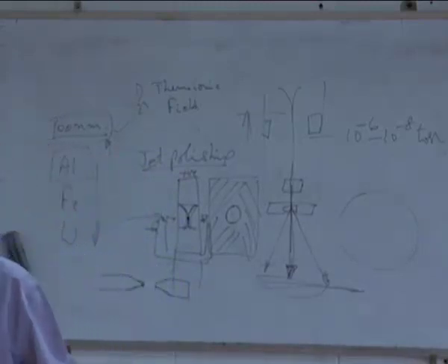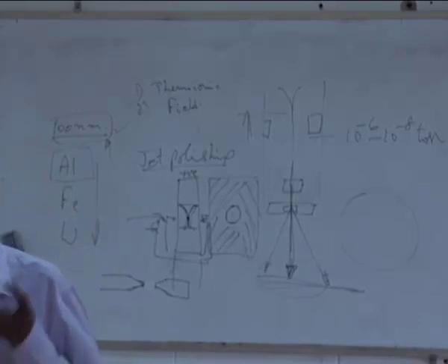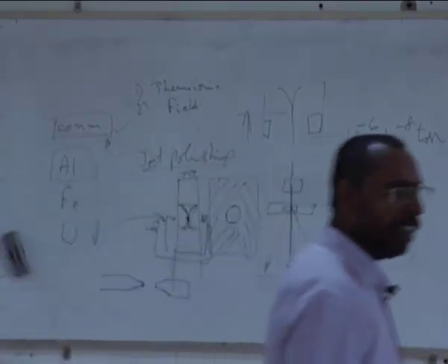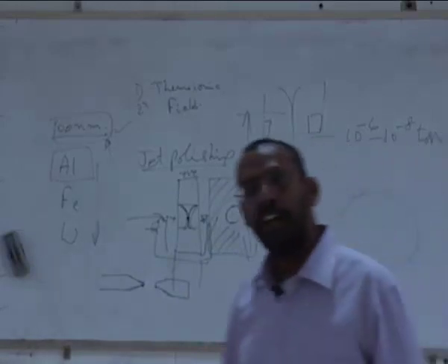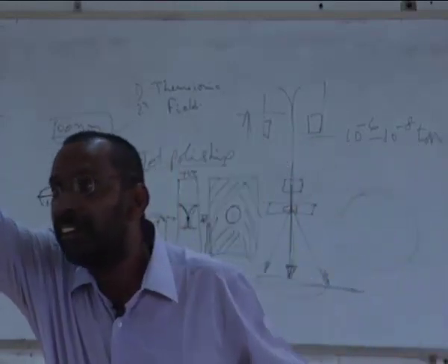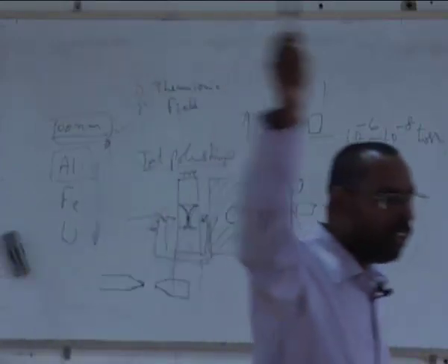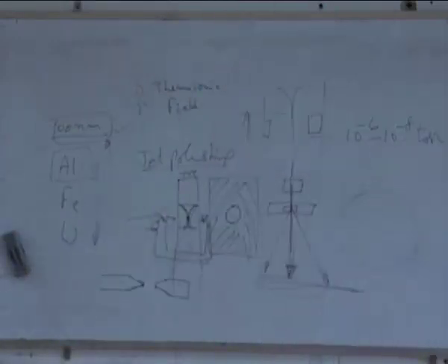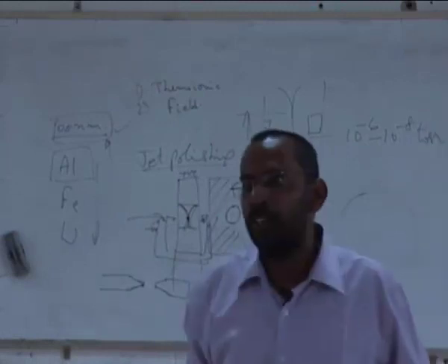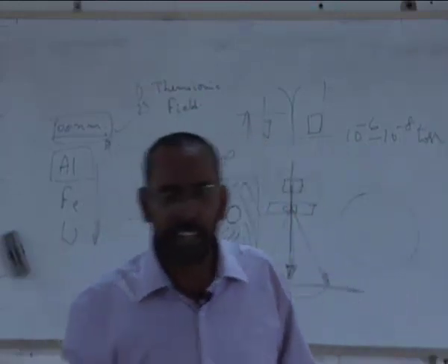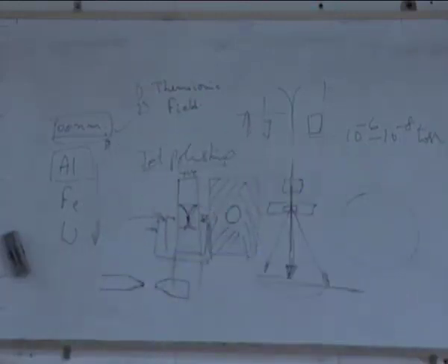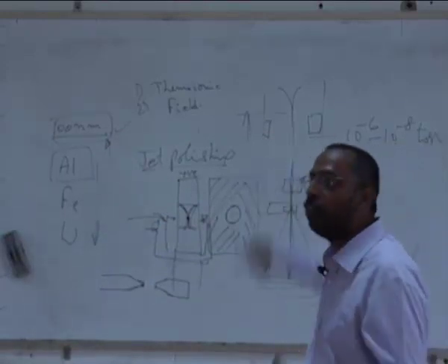But all this is possible only under one condition. What is the condition that is required for doing such an electro polishing or jet polishing? Yeah, selective dissolution. Anything more? There has to be a certain property of your sample. Should the sample be non-conducting? The sample should be conducting. If the sample is not conducting, there is no anodic dissolution.